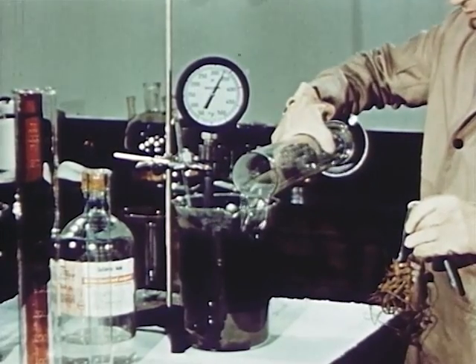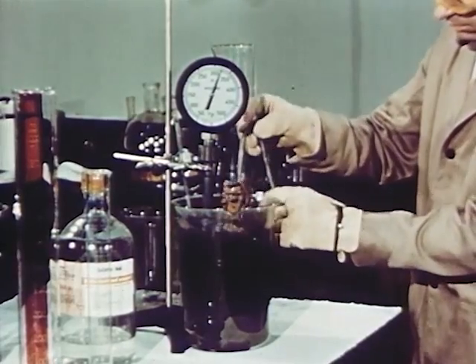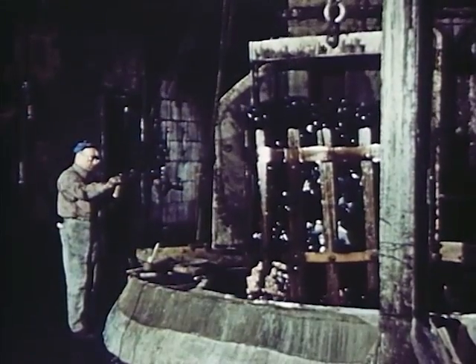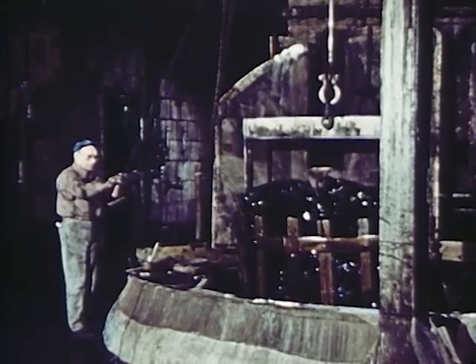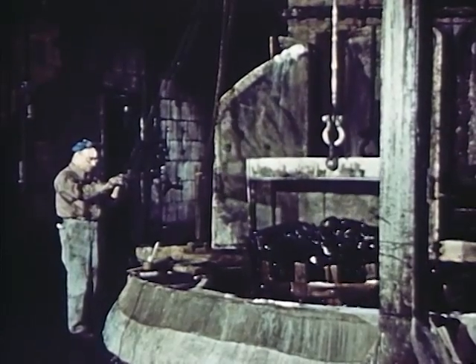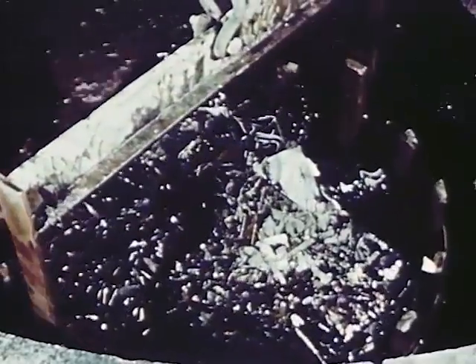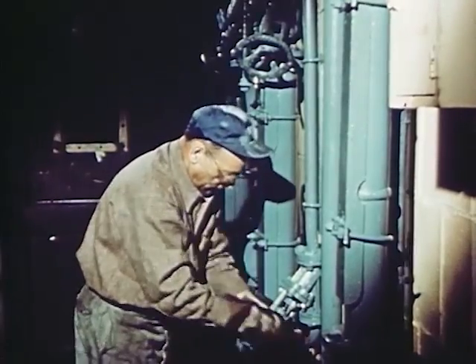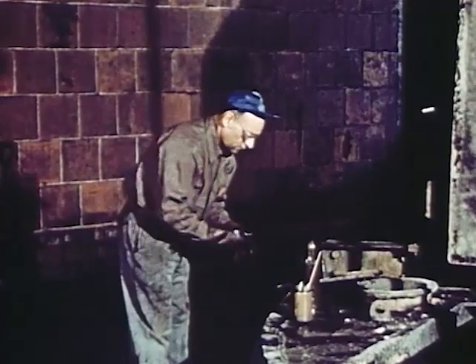At this time, a small amount of scrap iron is added to reduce chemically the iron in solution and so prevent it from oxidizing and becoming a source of contamination. In actual production, in a tank over 17,000 times the size of the laboratory glass beaker, it takes 15 hours for the maximum amount of ore to be dissolved. And this is only one tank in the battery of similar tanks that must be used and staggered for continuous volume production. Throughout, the specific gravity, acid strength, and temperatures must be regulated, and the solution analyzed to note what is happening to the titanium, iron, and sulfuric acid.